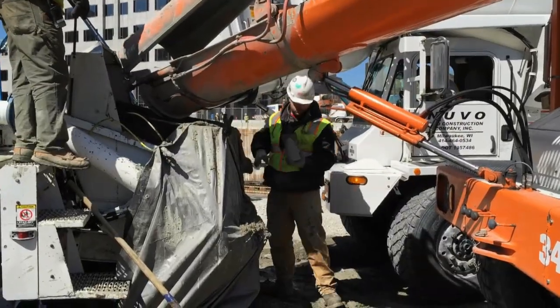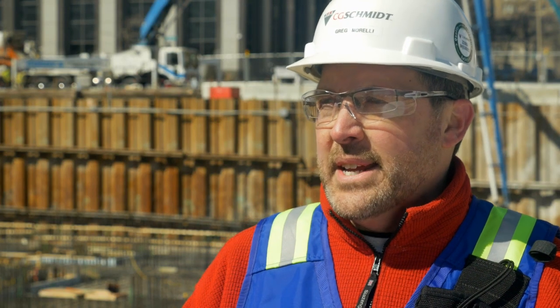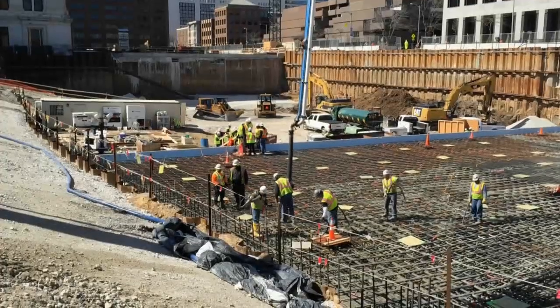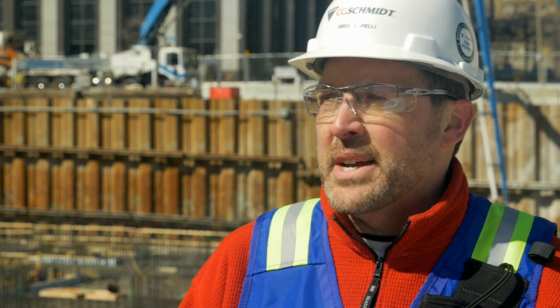On a pour like this, there's a real concern about the heating process in the concrete. So in the deepest part of the slab, we've got about 18,000 feet of cooling tubing. We put 22 temperature monitors in the concrete, so we're monitoring all the concrete temperatures. As it cures over the next week or so, we'll be piping cold water through the slab, circulating that to make sure we don't ever get too hot too fast in the curing process.